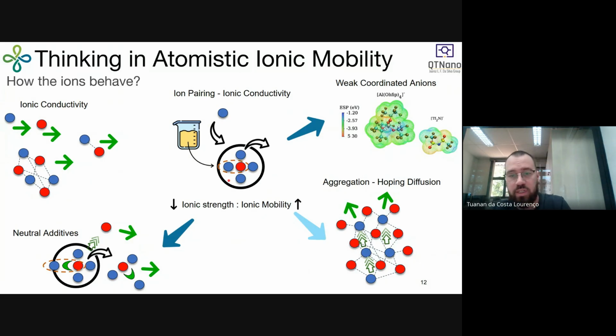If we think about a salt in water, something like that, we are going to see this kind of solvation shell in which we have the anion and the cations around the anion. But keep in mind that the solvation shell inside the electrolyte is a living structure. So this interaction here is always breaking and reforming. That means that one cation can go inside of the solvation shell, another go outside. So this is always changing and exchanging ions with different solvation shells. So if we understand how to control this interaction, how to control the solvation shell, we can improve ionic conductivity.